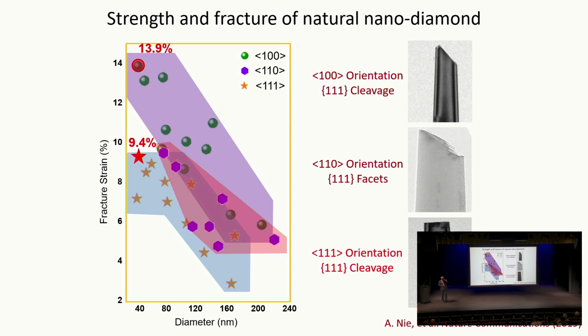They used focused ion beam to cut the diamond into nano pillars, and they had different crystallographic orientations: 100, 111, 110, etc. They pretty much repeated our experiments, and they did some other very clever things, and they showed exactly what we found. They showed that the fracture strain they got was 9.4% in their natural diamond experiments.